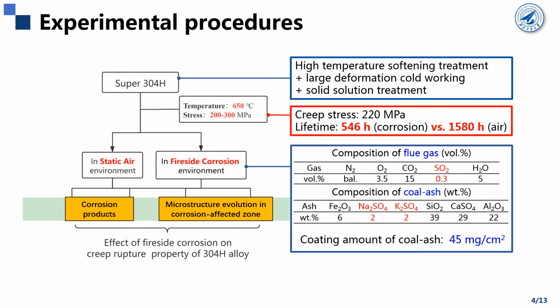In this study, Super 304H steel was applied as the raw material, and its creep rupture life was tested in static air environment and in fireside corrosion environment respectively. Then we can obtain the creep rupture life, for example, under the stress level of 220 megapascal. The lifetime is determined to be 546 hours in the corrosion environment versus 1580 hours in air. So that is a big reduction in creep rupture life.